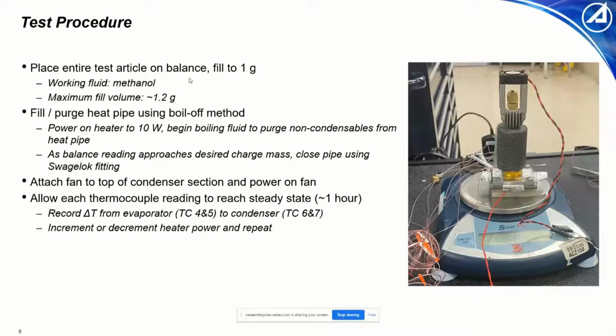After that, we would record the temperature drop, the delta T, from the evaporator, which was thermocouples 4 and 5, to the condenser, thermocouples 6 and 7. Then we would increment or decrement the heater power and repeat.